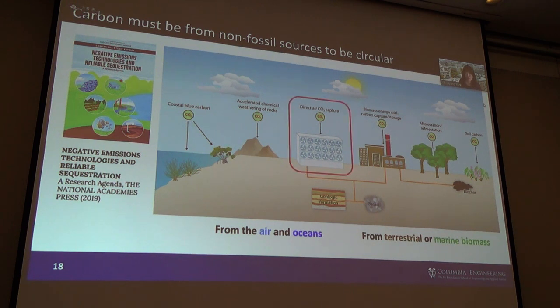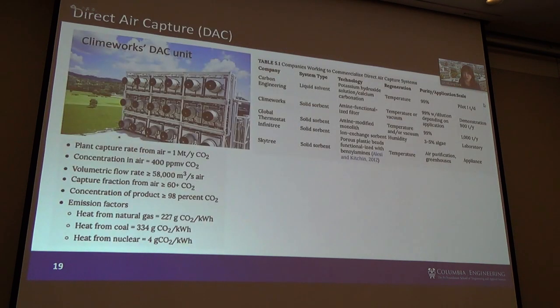But today I'd like to tell you a little bit about direct air capture we've been working on at Columbia University. The challenge of direct air capture is slightly different compared to point source capture. This is a photo of Climeworks in Switzerland, one of the well-known direct air capture companies out there. They're really good at moving CO2 and they know how to do that very well. But they're still challenged by having the right materials to capture CO2 from 400 ppm, which is a big task. Because it's such a low concentration, we are not targeting 90-95% capture. It'd be more likely about 60% capture.